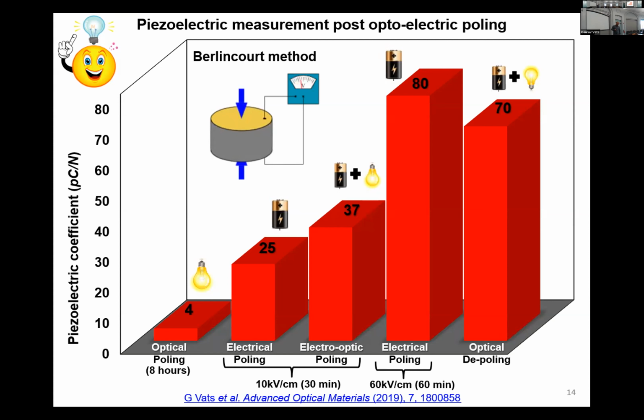Then we poled it electrically in the dark. We got a piezo response. Then we did the same thing, same parameters, same voltage, same time, but white light was also shining on the sample, and we see a difference here. So that means light is helping in poling the material.